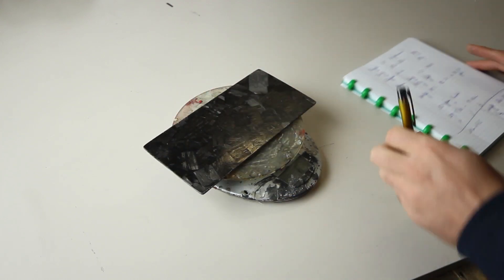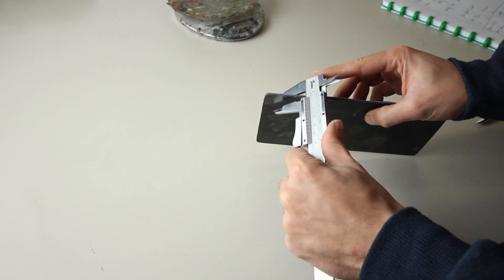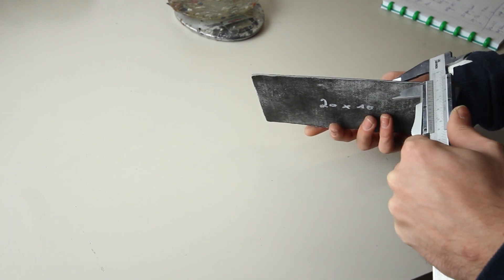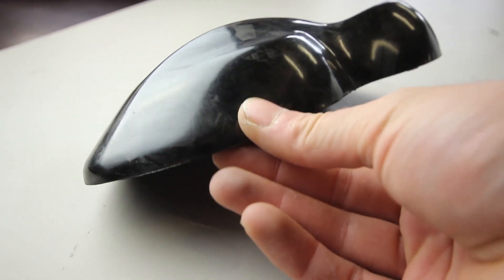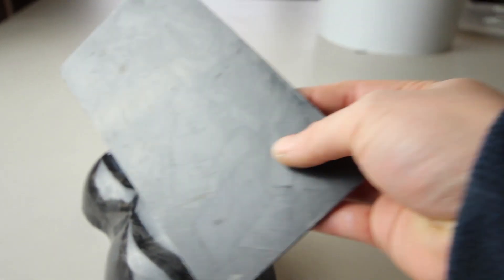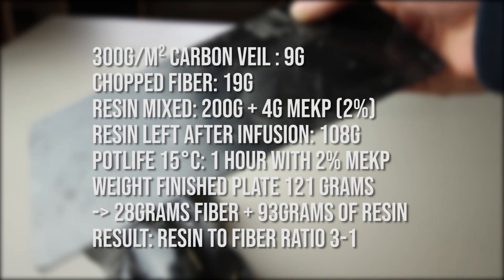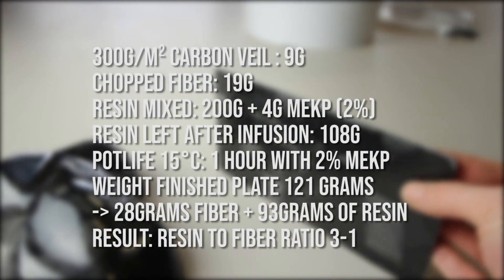I've cut out the part that we made in previous video at 20 centimeters by 40, just to know how much resin uptake it has - to measure right for one square meter. I also measure the thickness and you get about three millimeters of thickness with that 300 veil and chopped strands. Here once again the results - nice, I really like the pattern of the chopped fibers here. I'm pretty stoked with the 10 by 30 millimeters chopped strands from Easy Composites.